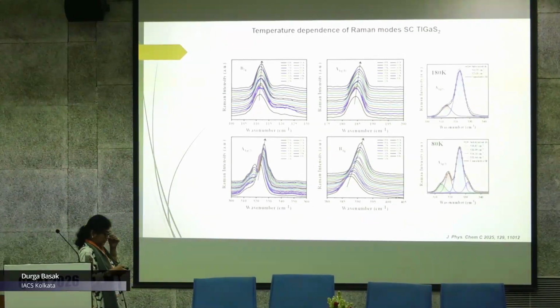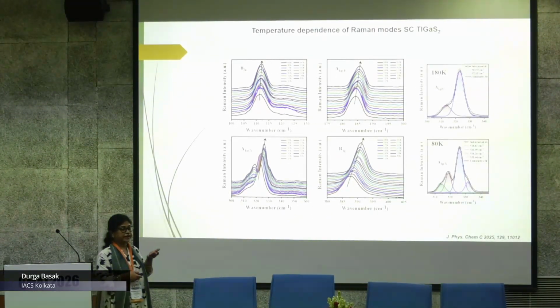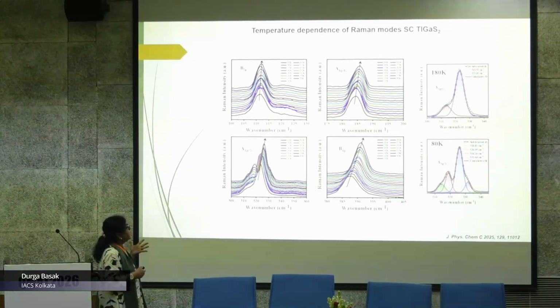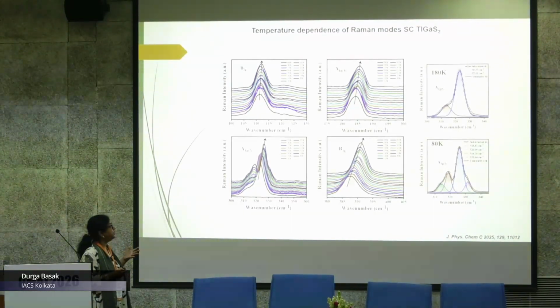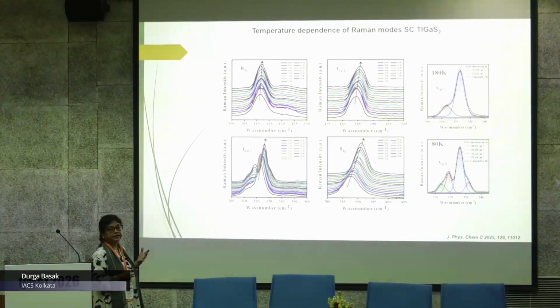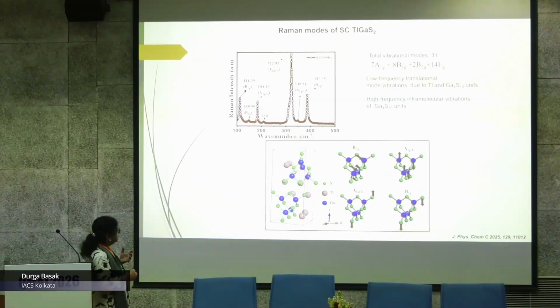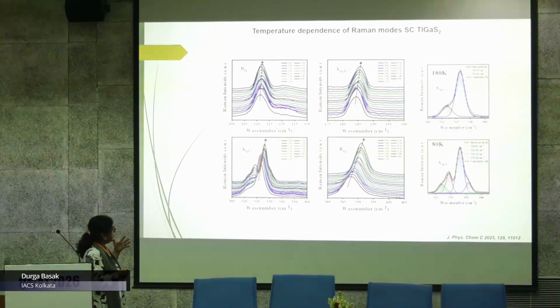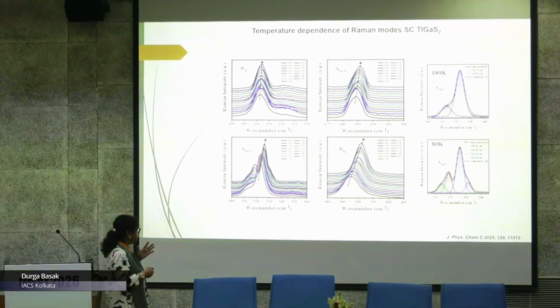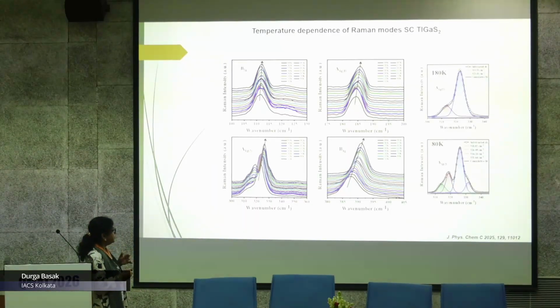So in order to get deeper insight into the phonon dynamics, we have taken the Raman modes at different temperatures. It shows that with decrease in temperature, there is a blue shift in the vibrational modes. I need to say that we have chosen these 4 intense peaks for this study, and in all 4 there is a shift to higher frequency as we go to the cryogenic temperature, down to 80 Kelvin. So there is a blue shift.